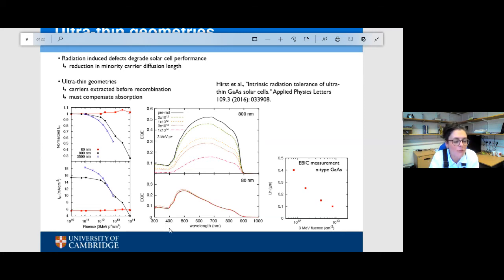Arguably, though, you could say even in this instance of a very low beginning of life performance, there could be situations where an ultra thin device would be preferable. So as I mentioned right at the start, your end of life performance is actually what limits what you can do in terms of payload. And so if you were going into very high radiation environments and you needed a long lifetime, there would be an argument to say, well, I can take that sacrifice at the beginning of life. What I need is sustained performance, because you can actually see that the 80 nanometer performance ultimately exceeds that of the thicker devices because of this effect.